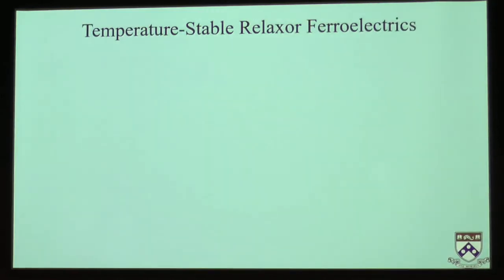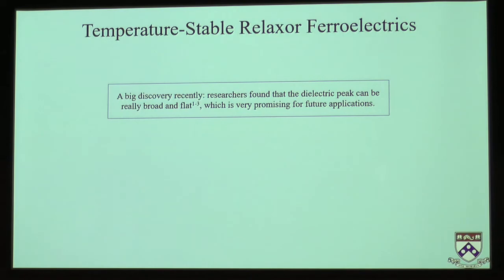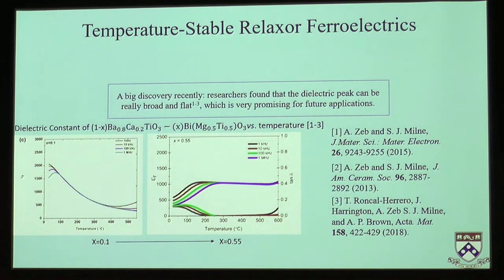So what makes our topic today different from previous topics? Our topic today is temperature stable relaxor. So recently, researchers at the University of Leeds found that they can engineer the dielectric peak into very flat and really broad. So this is super amazing for future technology applications. So how did they do this? They alloy the BCT and the BMT and measure the dielectric response at different temperature.